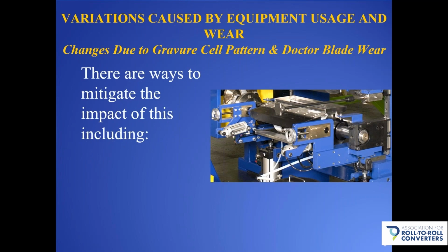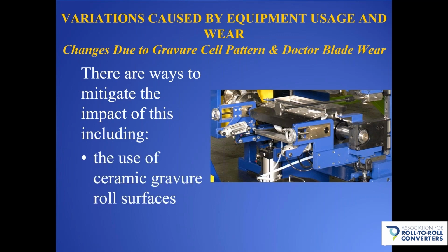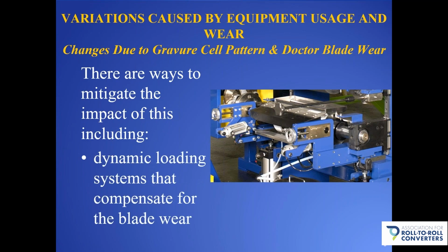So how do we address this? What can we do to mitigate the impact of this? Well, it's a couple of things. You can use ceramic gravure roll surfaces. Though they're more costly, because of their hardness, they obviously don't wear as fast. So therefore, you get a better and more consistent coating over a longer life. The other thing you can do is use a dynamic loading system on your blade that compensates for the wear in that blade so that you get a uniform and even and consistent wipe of the rolls.